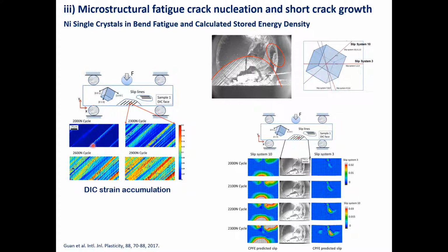And we see the development of these slip traces, which then grow and develop in intensity, indicating the progressive development of strain. And in this region where the slip develops, you can see on the front surface of the sample here, it's activated. Those slip traces are the very same ones you can see here. It's a single slip system activated with a very defined region of activation.